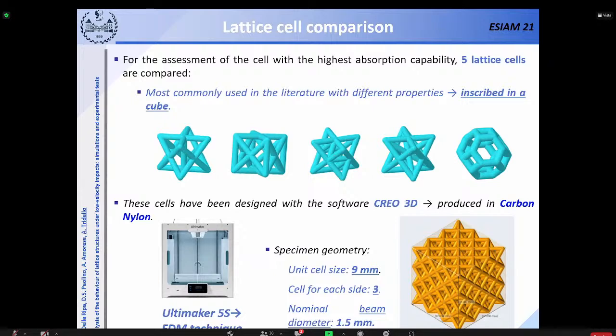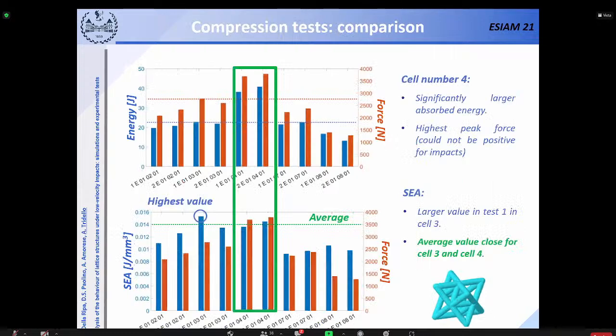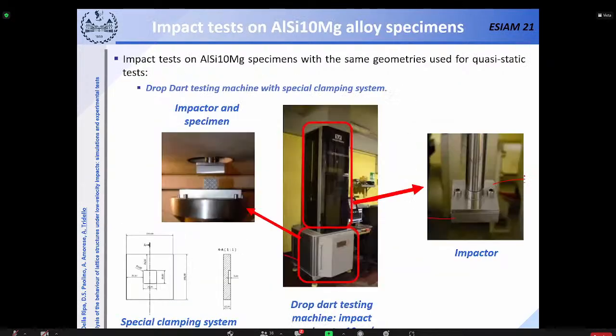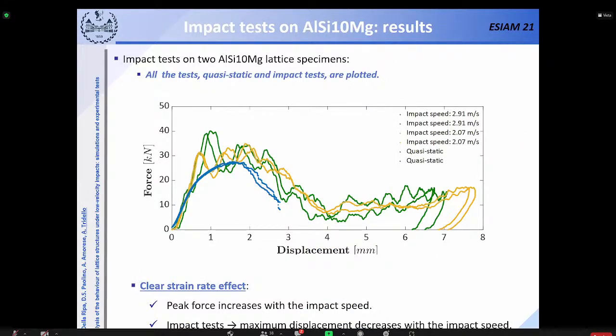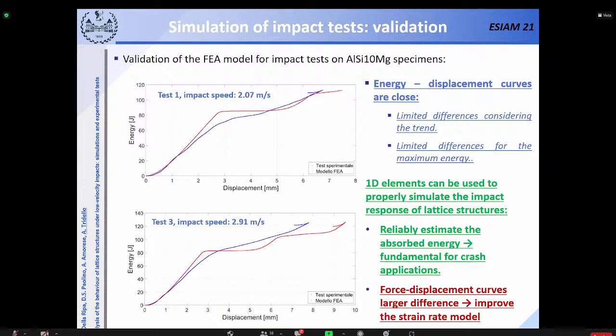How about the material properties when it comes to the rate dependency? Did you perform any more testing to get the material properties? Well, we ran tests at three velocities, 2 repetitions each for each velocity, and we put in the Johnson-Cook model the values that we got with these three values of velocity, and finally we got something in quite good agreement in terms of absorbed energy, but indeed the part related to the aluminum alloys has to be developed a lot, since I cannot tell you we got good results in terms of modeling.